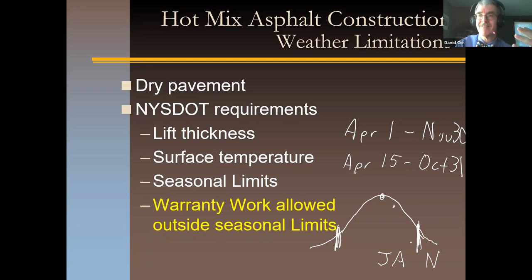So as you're thinking about when you want to pave, the closer to the middle of the summer, the better. Now, this has been a hot year. We're going to get probably a little bit longer paving season, but watch that weather real carefully, because if that ground temperature starts to get cool, you're going to have problems. You don't need temperature just the day you pave. You really want it for some time afterwards so that the asphalt concrete has time to really set up properly and traffic finishes the job. So be careful about the limits. Pave closer to the season than you can. And that's for hot mix.